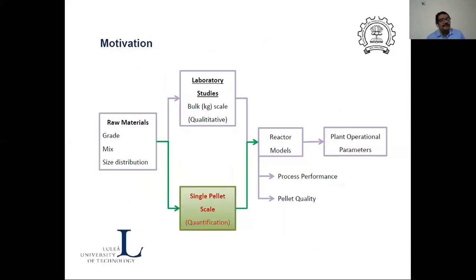So what was the motivation for doing this problem was, if you look at the whole reactor, the induration reactor, there are two kinds of reactors, straight grate and the kiln one. Because this is actually a moving bed, and the pellets are stacked in a bed like this, the properties of the pellets can vary from top to bottom. Because the temperature and the gas composition the pellet encounters is not going to be the same throughout the whole section of the bed. So then the quality of the pellet varies.